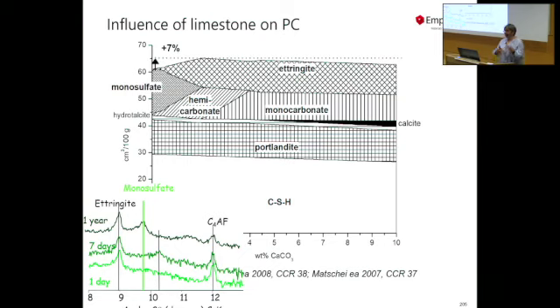And basically what happens if we add calcite or limestone into our mix is that a little bit of the limestone reacts. And the cool thing it does is stabilize monocarbonate and leave all the sulfur there to make ettringite. So it's the combination, and as you all know, ettringite is a very good space-filling material. We can also calculate an increase in the volume. If you look at the total sum, we have a small increase in volume, and I will show you in the next slide that this can also be translated into higher compressive strength.